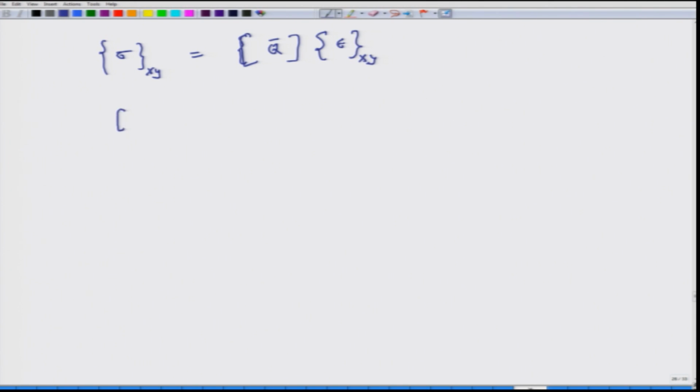And to recap, Q bar matrix is nothing but the inverse of transformation matrix T1 times Q matrix times transformation matrix T2. We know what exactly the T1 matrix is, so we can take its inverse, and we know what the T2 matrix is.